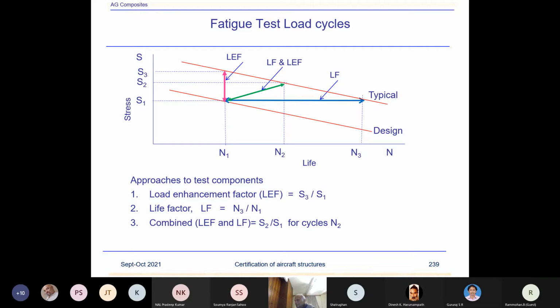So one would consider various modes of failure and decide the value of the load enhancement factors and the life factors. Life factor normally we want to exceed two design lives. It's a load enhancement factor. Based on the scatter, we'll determine and try to see what is the dominant failure mode in our structure. Suppose we have the flaps. We will evaluate the joints, load enhancement factor based on the joints, fatigue, BVID fatigue, open hole fatigue, and then compile the information and determine what load enhancement factor we have to apply.